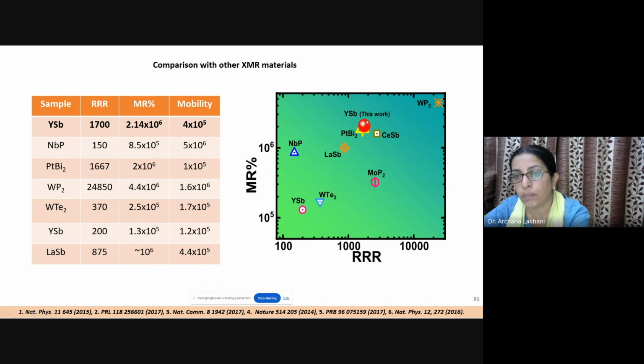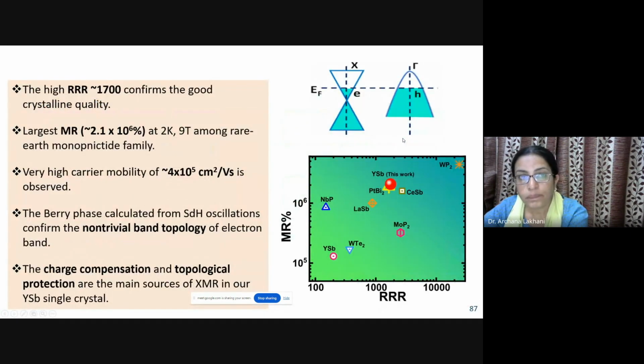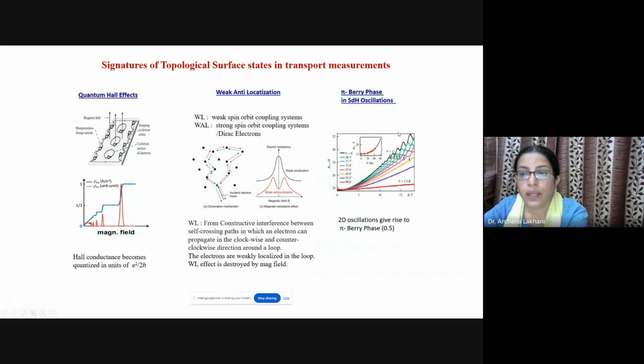This red mark shows that we have very high magnetic resistance in comparison to most of the known XMR materials already in literature. So if you see, except WP2, we have the highest XMR in this particular sample. So there are other interesting signatures also which we could see in transport measurements, which can be seen in these